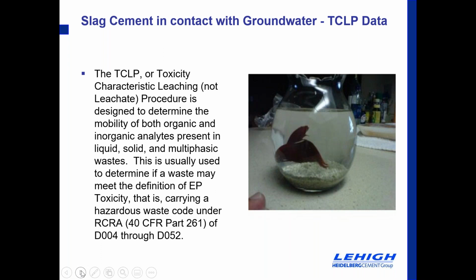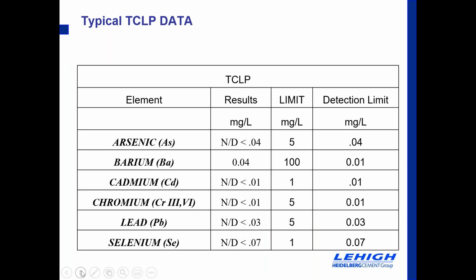So, next slide. The details behind that are shown here. Here we have heavy metals: arsenic, barium, cadmium, chromium, lead, selenium, and we're showing the typical results we see. In most cases, non-detectable. Barium still very low, but the limit obviously is substantially higher. So this is one of the reasons why we're involved in so many geo projects where they're trying to capture or tie up elements in the ground.